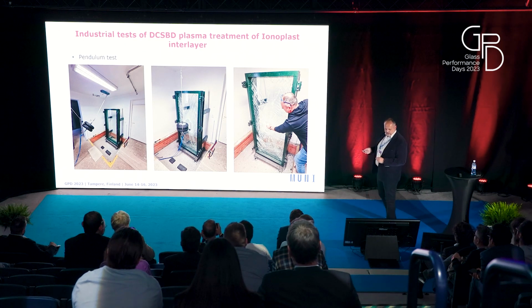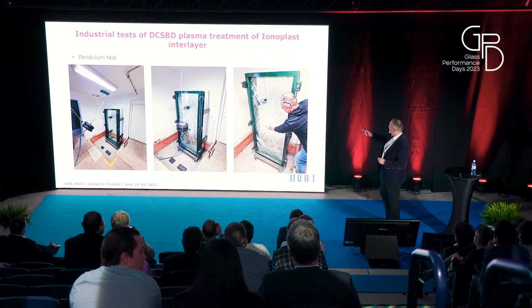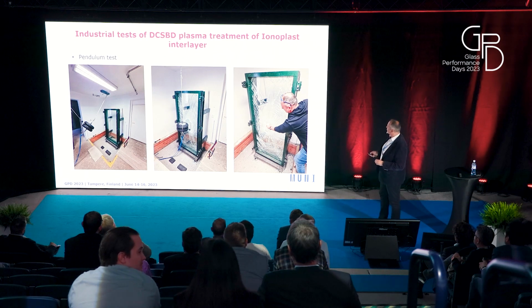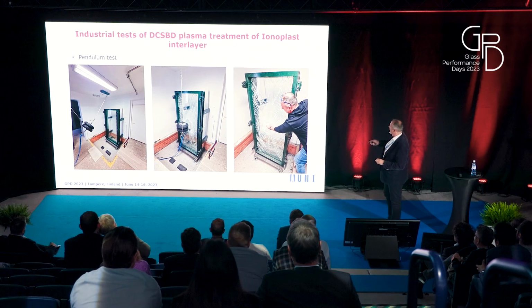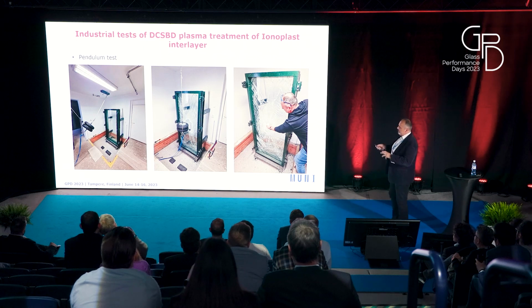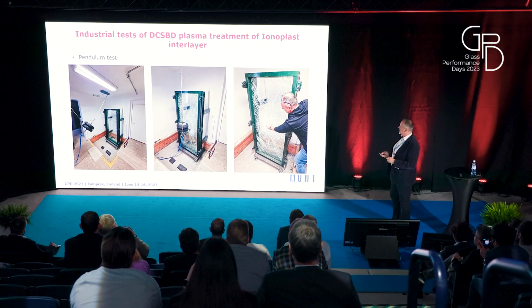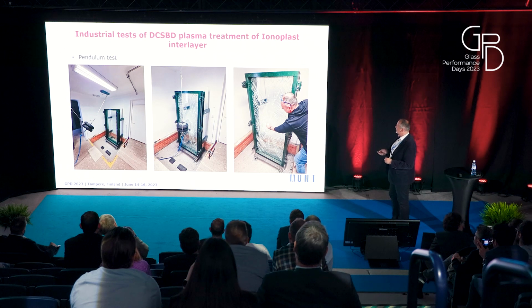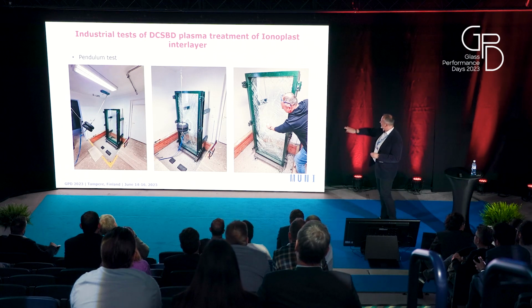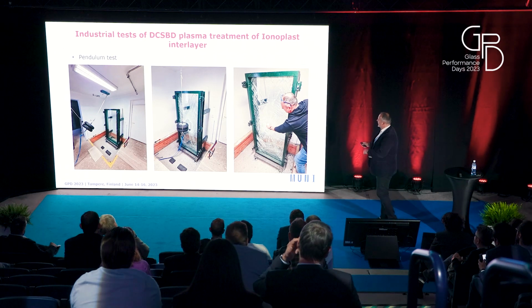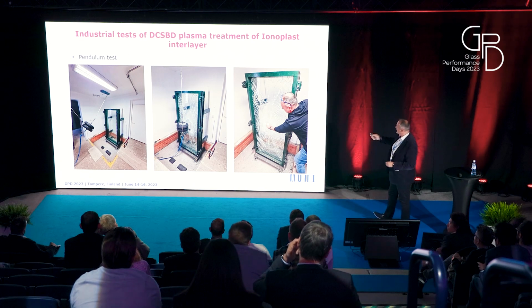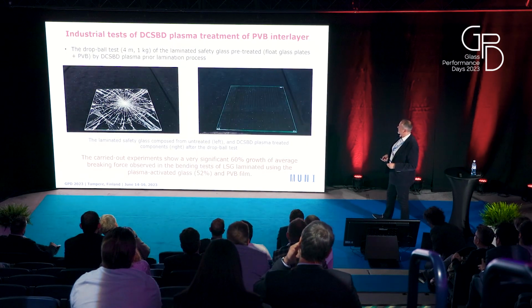You can see on the last photo that for laminated glass which was prepared using plasma treatment of glass and also SentryGlas, after the test it was not possible to put the testing bolt through the glass, so it was successful.